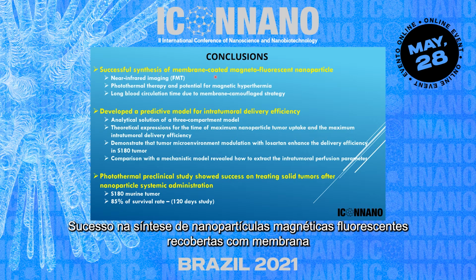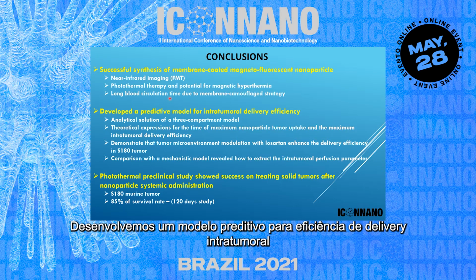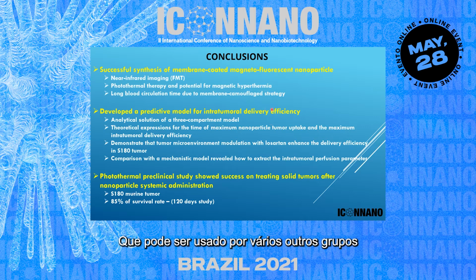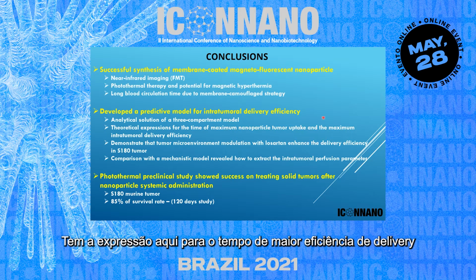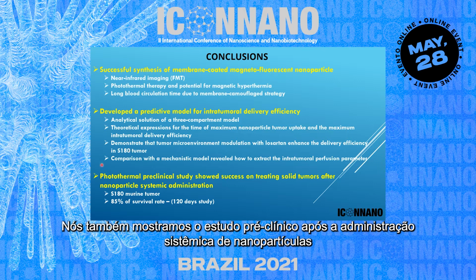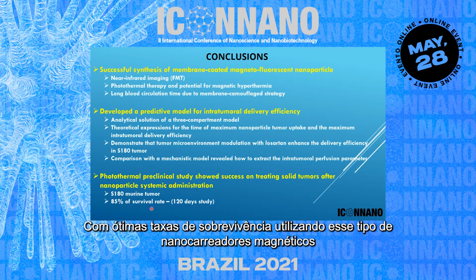this membrane camouflage magnetofluorescent nanoparticles. We had developed a predictive model for intratumor delivery efficiencies, which can be useful for several other groups. There are expressions here for the time of highest delivery efficiency. We also showed that the photothermal preclinical study after nanoparticle systemic administration, great survival rate using this type of magnetic nanocarriers.